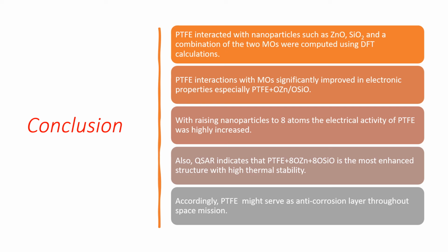So we can conclude our work that polytetrafluoroethylene interacted with nanoparticles such as zinc oxide, silicon dioxide, and a combination of the two metal oxides were computed using DFT calculations. Polytetrafluoroethylene interactions with metal oxide significantly improved electronic properties, especially polytetrafluoroethylene interacted with zinc oxide, then silicon dioxide.